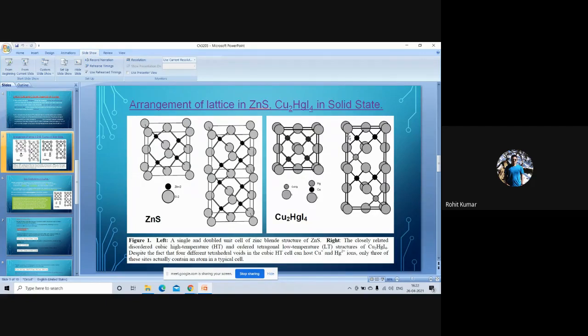So basically, we have seen that at low temperature copper tetraiodomercurate has a tetragonal lattice. The iodide ions form the FCC, and the copper and mercury cations are in the tetrahedral holes of the structure formed by the iodide ions. At this low temperature phase, the solid is brick red. But as the temperature increases, disorder happens, and this tetragonal unit cell starts to deform and forms a disordered cubic structure with one half of the volume of the tetragonal phase.